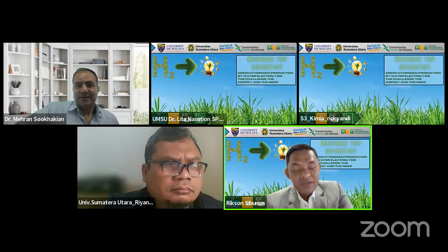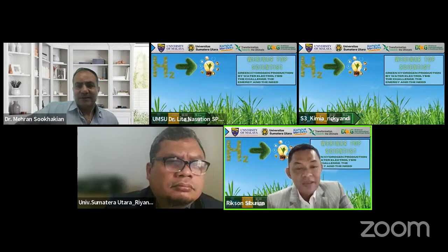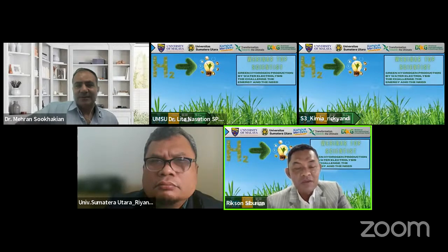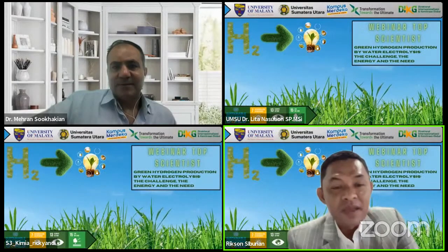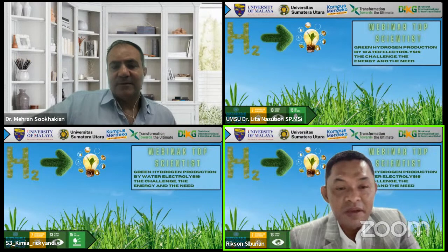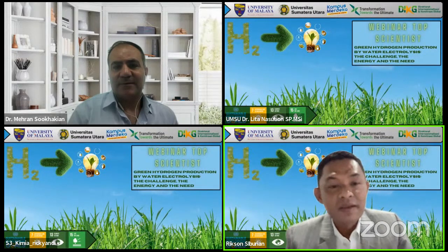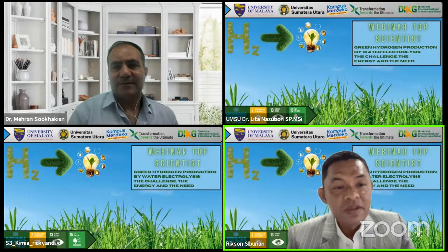In our case, if we use a catalyst like Pak Made's case, a fuel cell catalyst, platina, right? We have to think deeply about many conditions, because platina sometimes suddenly agglomerates at high temperature, and also some carbon black will aggregate at 600 degrees C. That's why previously we don't favor using high temperature for preparation of catalyst. We use chemicals like ethanol, and all is done at room temperature. So this is very interesting for me. Your data is very nice based on the TEM, even though you use CVD, right?